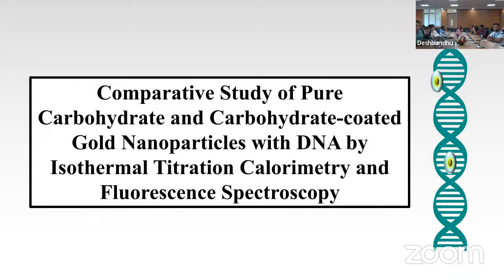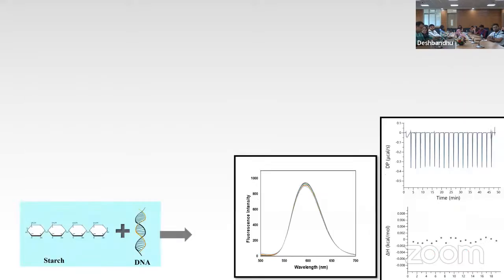In fluorescence spectroscopy, DNA shows a weak fluorescence, which is insufficient to study the fluorescence quenching mechanism. So we used ethidium bromide dye. Ethidium bromide is an intercalating dye which is used to study the intercalation of molecules in the DNA, to know the quenching of the fluorescence of the DNA-EtBr complex. The concentration of the nanoparticle was varied until complete quenching of the DNA-EtBr complex. So we have performed the fluorescence spectroscopy.